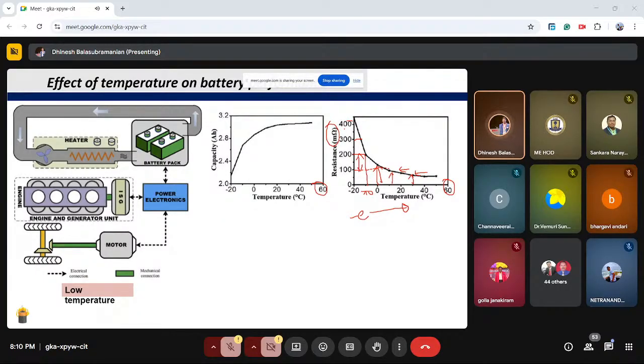When you look in parallel at this resistance and the capacity of your battery, as the temperature is higher, the capacity of your battery lies close to 3.2 to 4 Ah in general. But as the temperature slowly decreases, the capacity of your battery also gets reduced. This is because as the lithium moves in the horizontal direction, it sticks on the graphite area and doesn't get back to its original position. This is what is referred to as lithium plating.